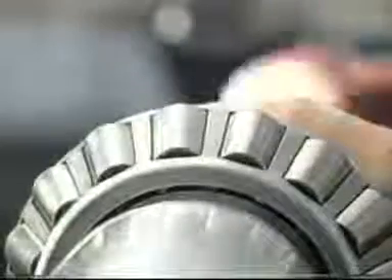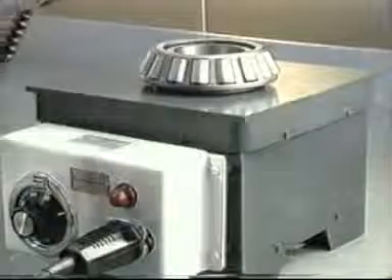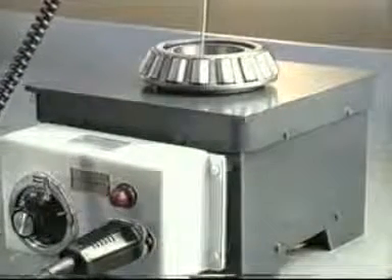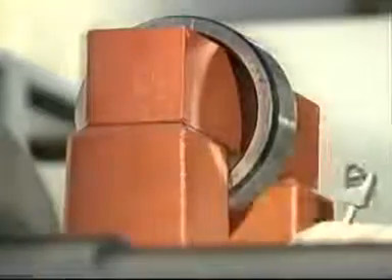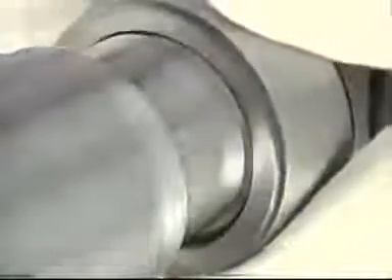When you cold mount small rings, everything we already said still applies, and you use the same equipment as well. You do this job much better and be kinder to the fitting surfaces in the process if you heat the ring and then shrink it on the seat. You can do this here as well with a heating plate, an inductive heating device, or an oil bath. Forgive us for repeating ourselves, but it's important. Never get it any hotter than 120 degrees Celsius or 248 degrees Fahrenheit.